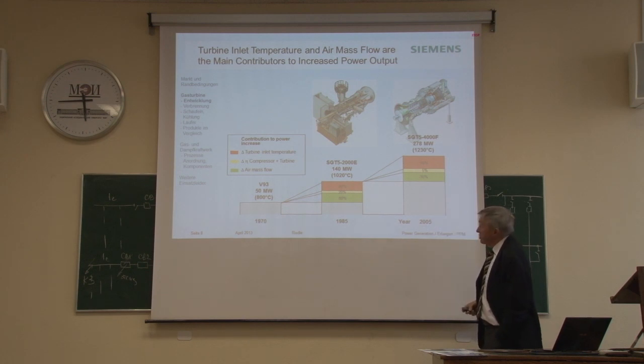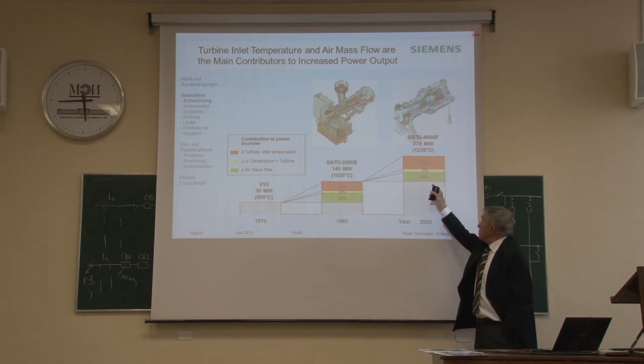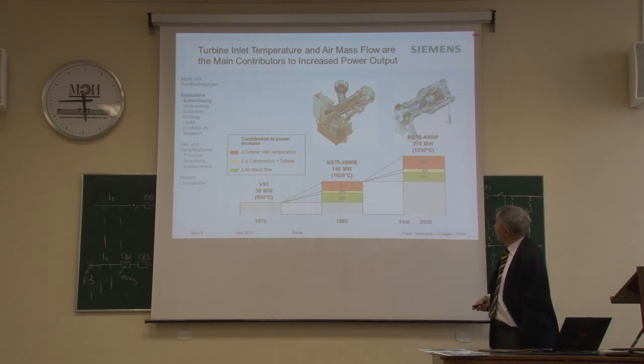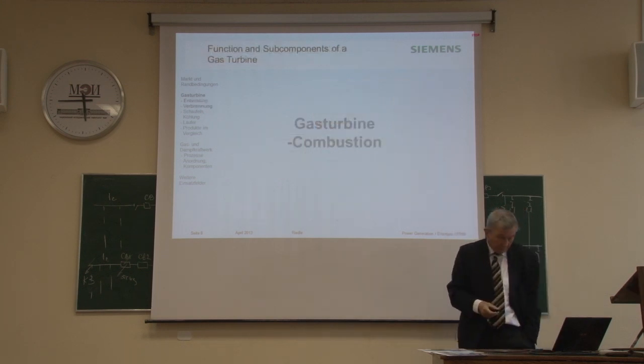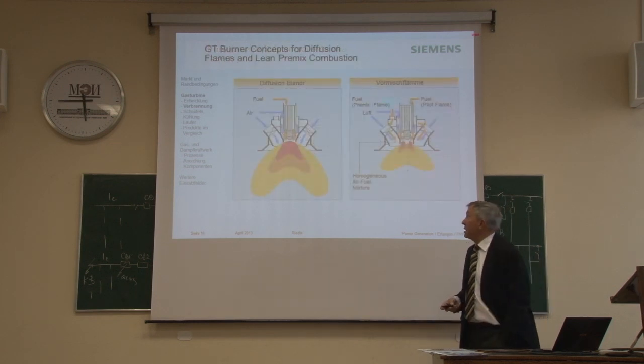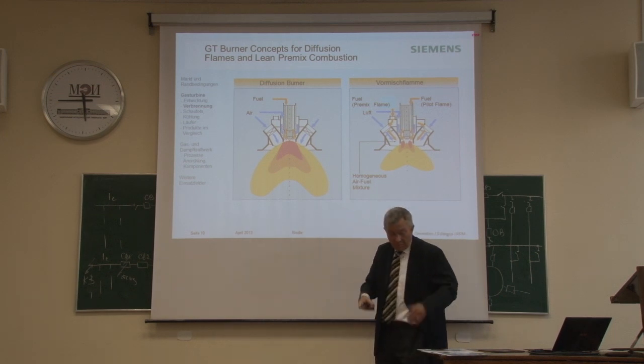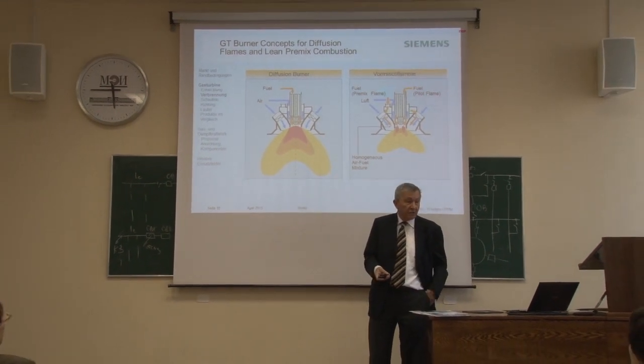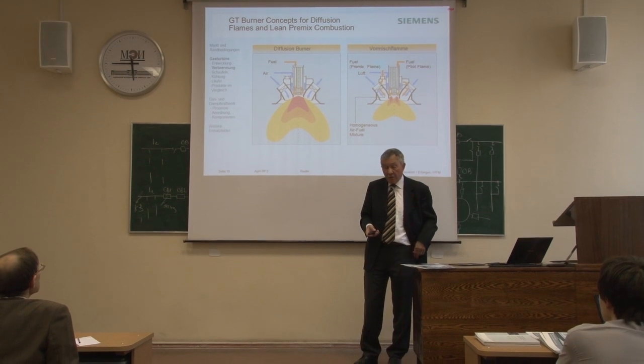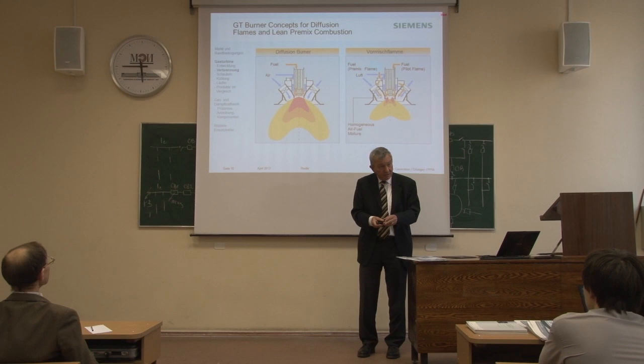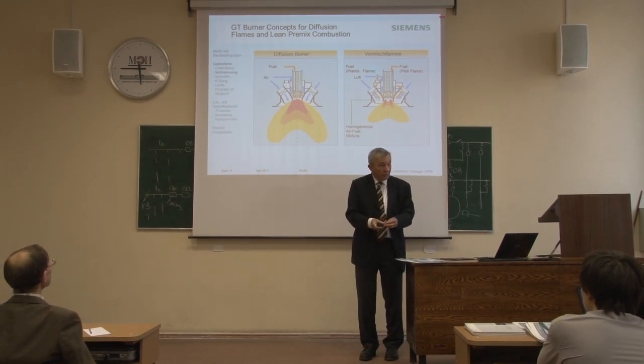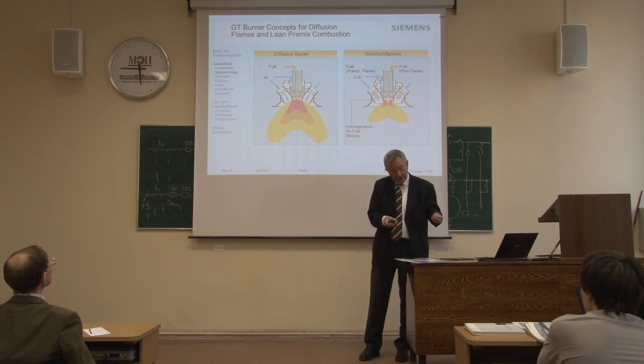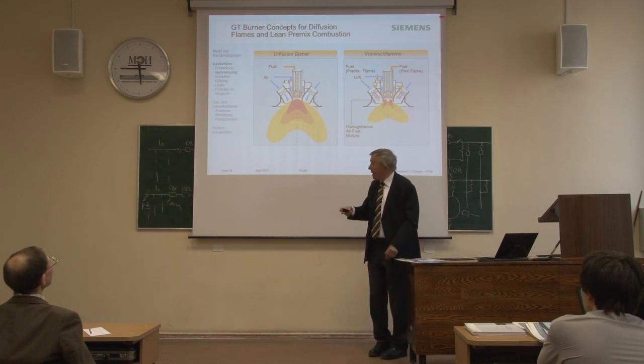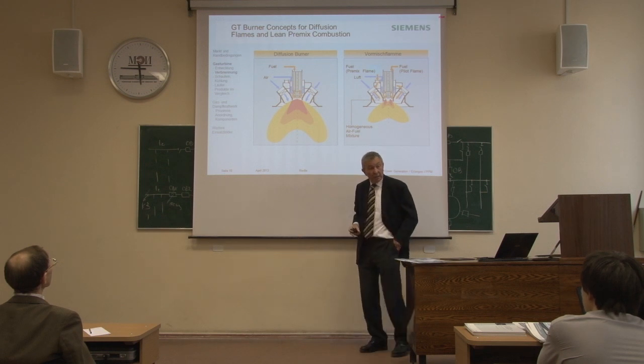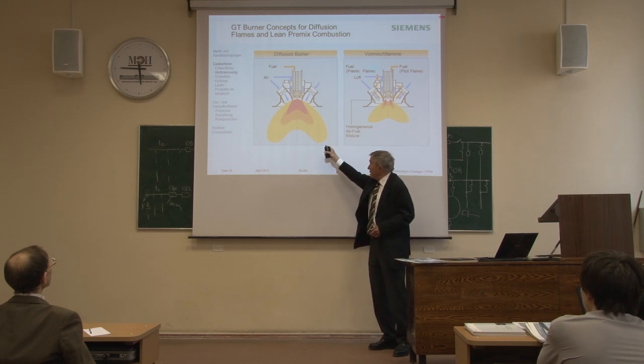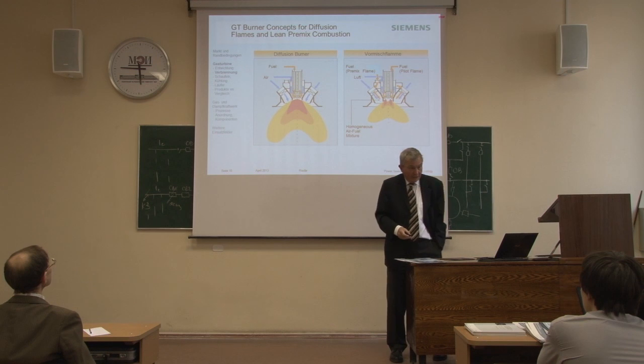And in 2005, you saw we increased the temperature another 200 degrees. Again, the contribution from increased mass flow, better efficiency of the component, and higher temperature. I mentioned combustion is not that trivial a problem. In old days, you took just the normal gas and fired it like you have a burner at your stove. And every particle of the natural gas collects enough air and oxygen to burn. That means for a moment you have an air-fuel ratio of 1, giving a very high adiabatic temperature. That's that reddish area. And then more air is mixing in, it cools it off till you get to the temperature with which the gas enters the gas turbine.